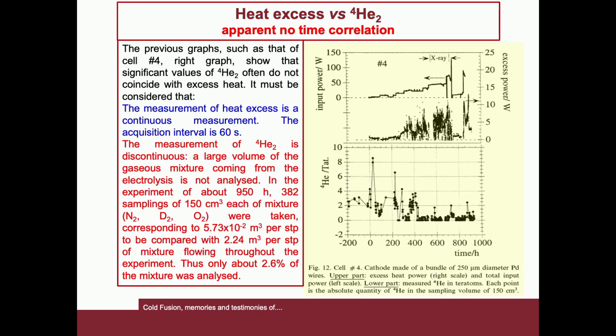Heat excess versus helium-4 and apparent no-time correlation. The previous graphs, such as the one for cell 4 reproduced here, show that significant values of helium-4 often do not coincide with excess heat. It must be considered that the measurement of excess heat is almost continuous. The acquisition interval is 60 seconds. The measurement of helium-4 is discontinuous. A large volume of the gaseous mixture coming from the electrolysis is not analyzed.